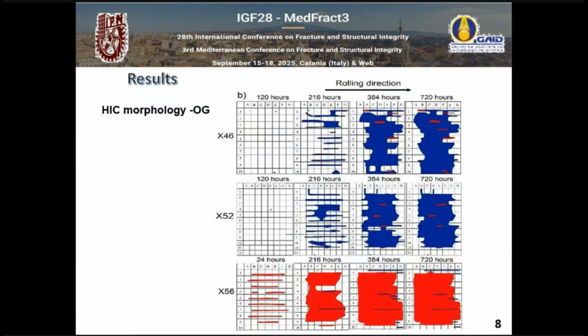And here is the result. Yes, the new generation steels can have HIC. These are the mappings. As we can see, we have this delayed nucleation. You can see this plate, this X56 steel, started to crack in the first 24 hours. It had some very well-developed cracks. Each of these small squares is 1 centimeter. So you can see in the X46 and X52 plates, we have very, very little HIC after 120 hours.